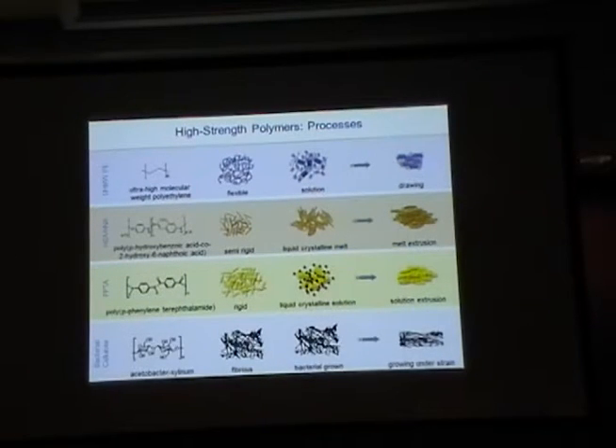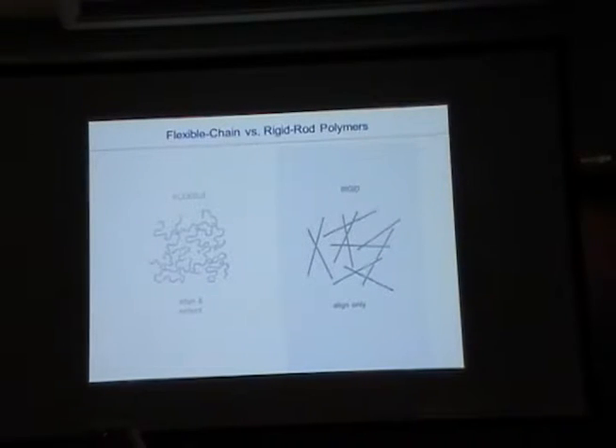In mechanics, people know that. So there are four different high-strength fibers. Polyethylene, you can make high-strength fibers. Completely different processing would than, for instance, Kevlar. So this is the chemical name for Kevlar, which is a rigid rod molecule, which is actually liquid crystalline in solution. Depending on their chain conformation and their chemistry, you need different processing rules. And this is something we don't exploit in electronics.